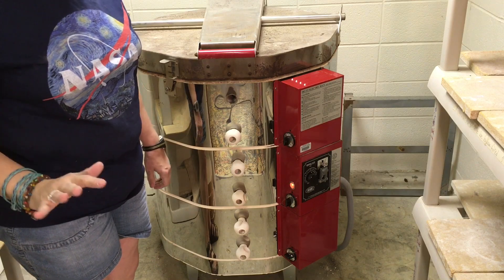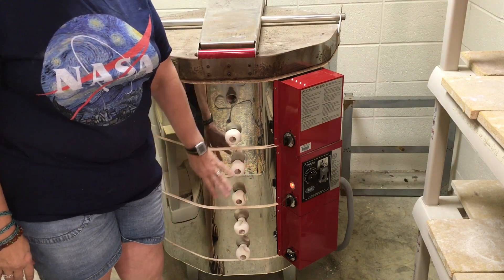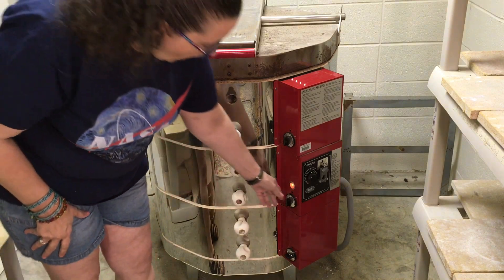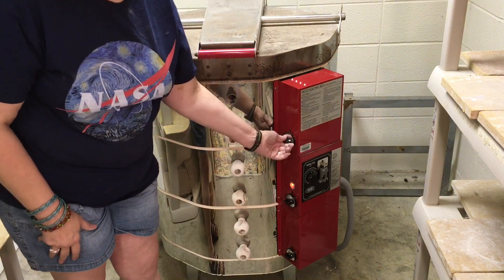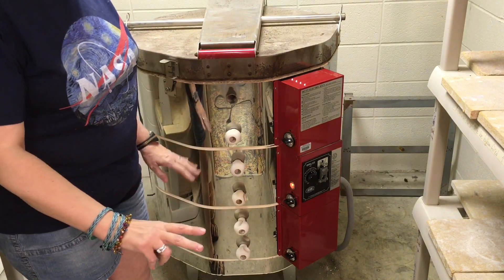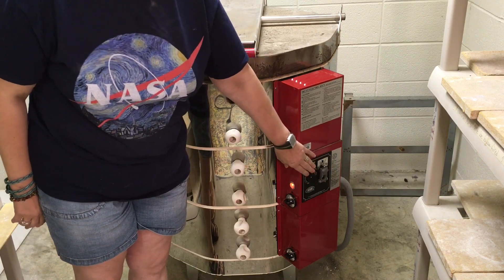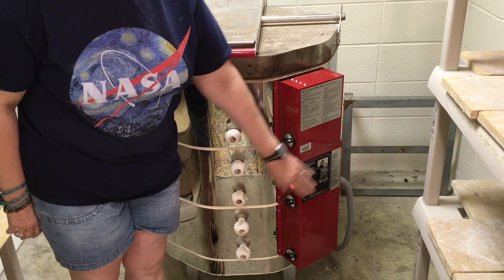When I come in the morning, the first thing I'm going to do is close all the peepholes but the top one. I will turn both of my other knobs up to low and leave it for two hours. You also need to make sure you turn up your timer so it doesn't time out on you after being left on overnight.